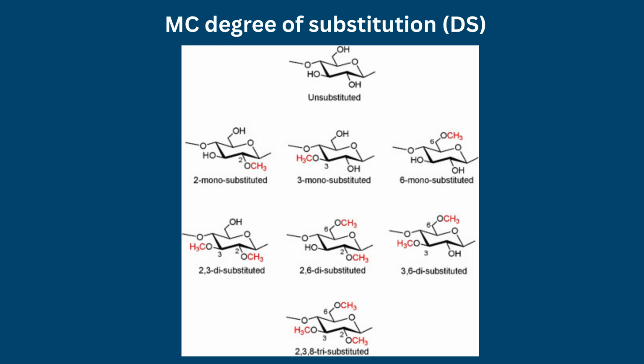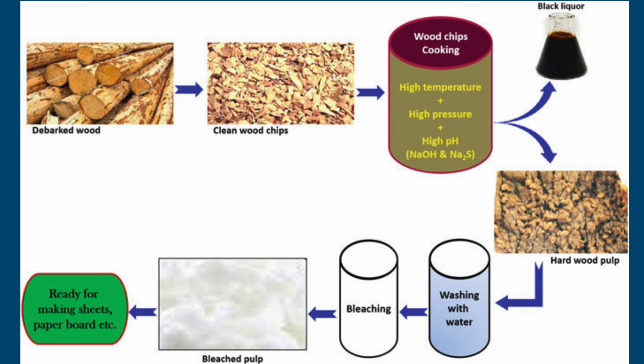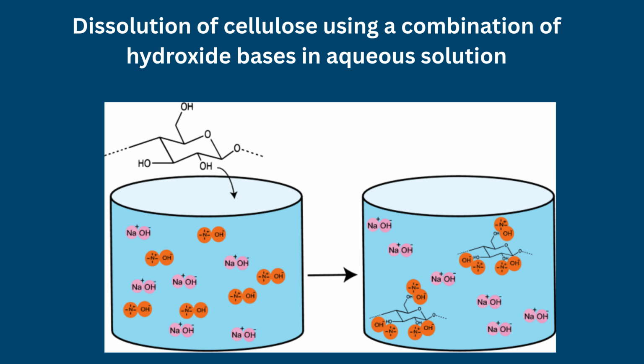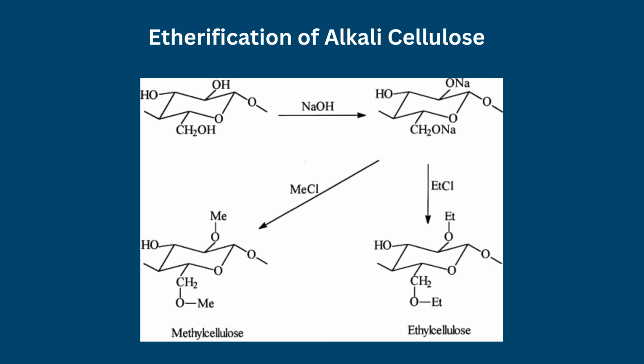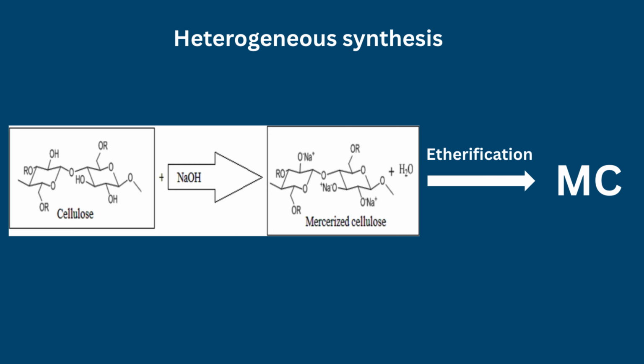Industrial production of MC begins with highly purified cellulose derived from wood pulp or cotton linters. Cellulose is first treated with sodium hydroxide to form alkali cellulose, which swells the cellulose fibers and increases hydroxyl accessibility. Etherification is subsequently carried out using methylating agents such as chloromethane, producing stable ether linkages. Careful control of reaction conditions allows manufacturers to tailor molecular weight, substitution pattern, and DS to obtain products with specific viscosities and functional properties. 2 principal synthetic approaches are employed.